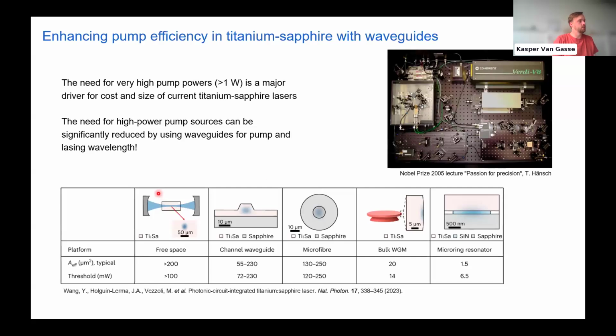Now the easiest way to do that is, you don't want to change the crystal because that works really well. You more want to change the way you pump it. When you pump something in free space, you're limited by how far you can focus it down, while also having a long length over which the beam is focused. And that causes the need for very high pump powers to reach a certain intensity. A very easy way to increase intensity while keeping the power the same, or even reducing the power, is using a waveguide, because it allows you to make the mode area very tiny over a very long length. And that allows you to have much higher intensity while keeping the power low.